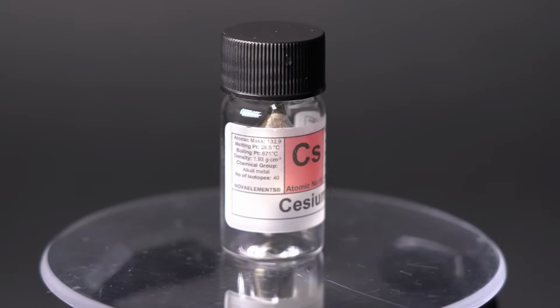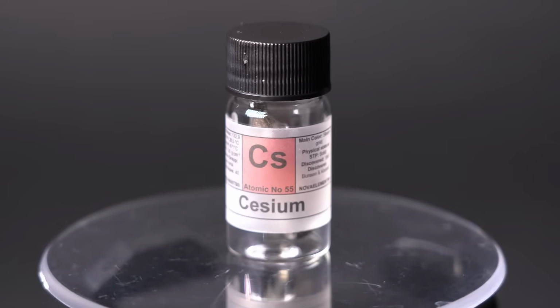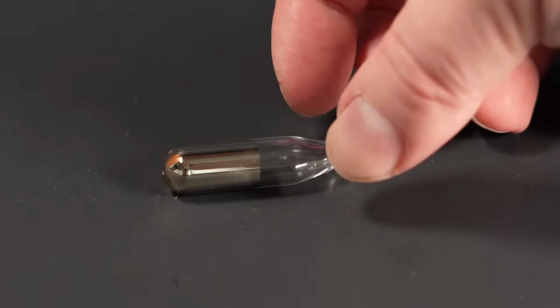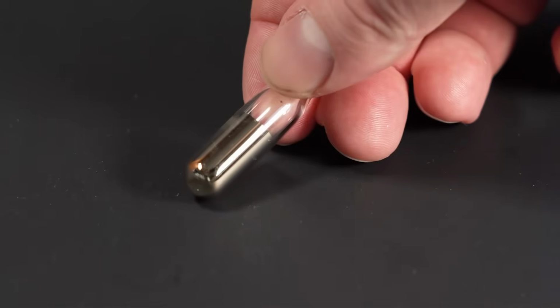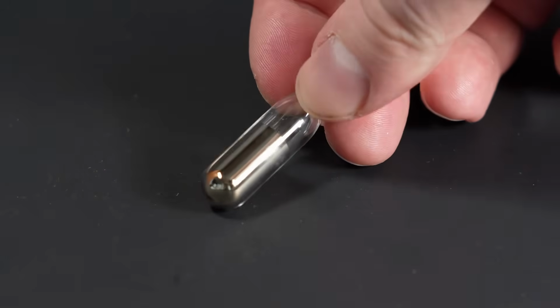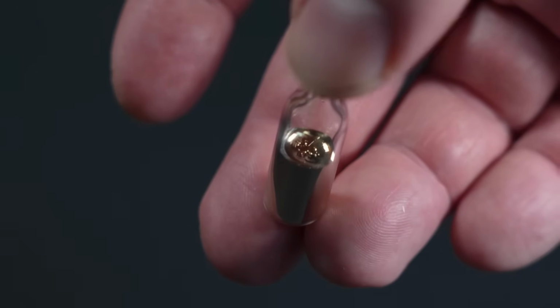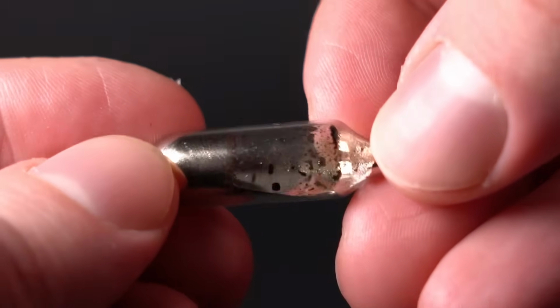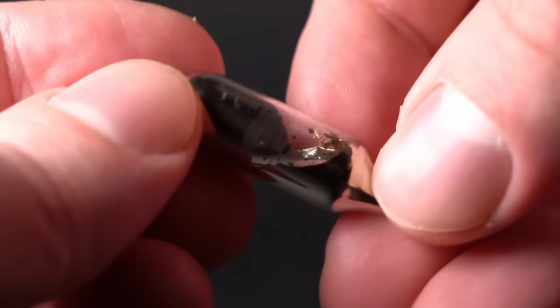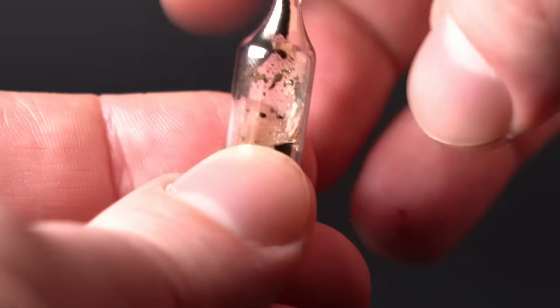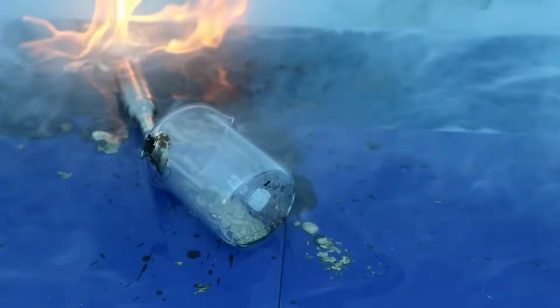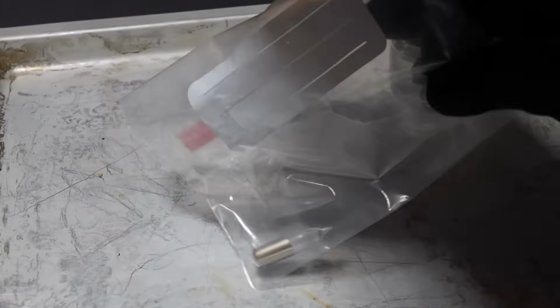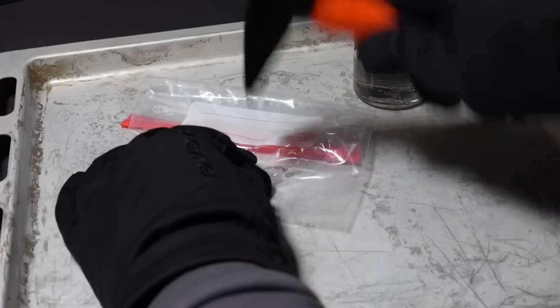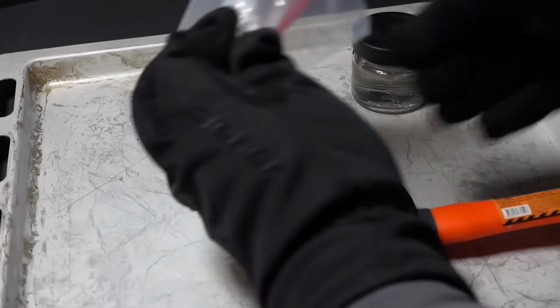And finally, I decided to boil the most reactive metal, cesium. Since such a reactive metal oxidizes even in the best mineral oil, I purchased it sealed in a glass ampoule under an argon atmosphere. The problem with cesium is that it is extremely reactive and also melts at just 28 degrees Celsius. And as soon as I break the ampoule, it will most likely melt from oxidation in the air and leak out. By the way, this actually happened to me a few years ago, and I would rather not repeat that incident. That's why I initially decided to cool the ampoule with cesium in the freezer and then break it inside a bag to contain the flying glass shards along with any remaining cesium.